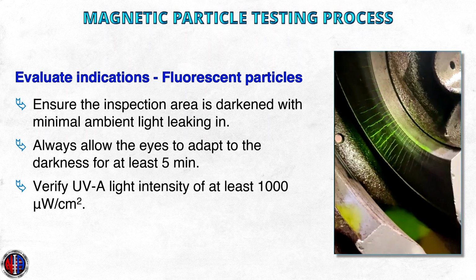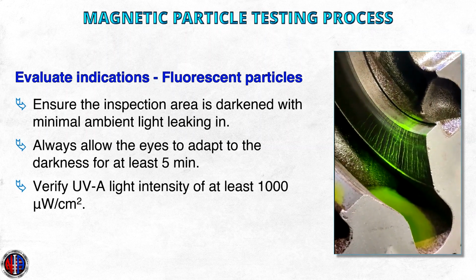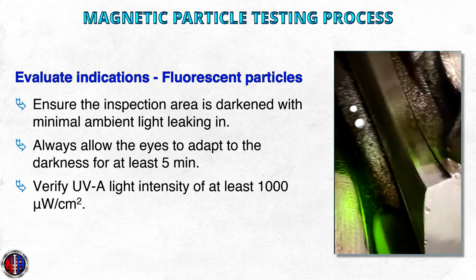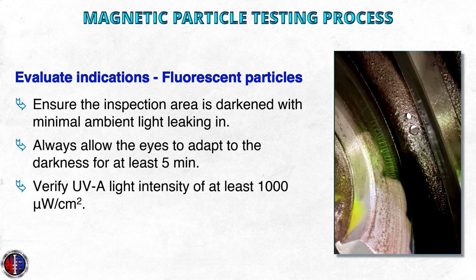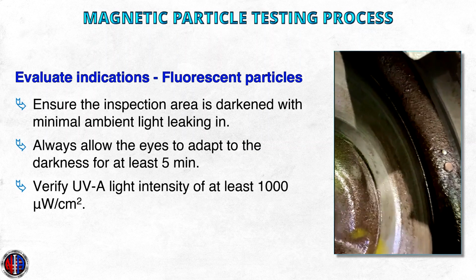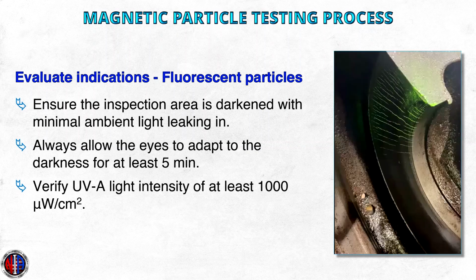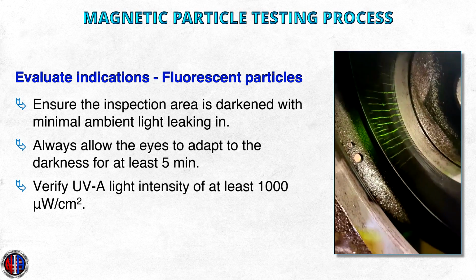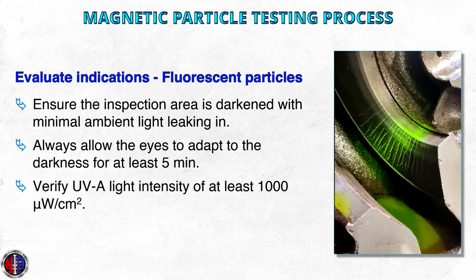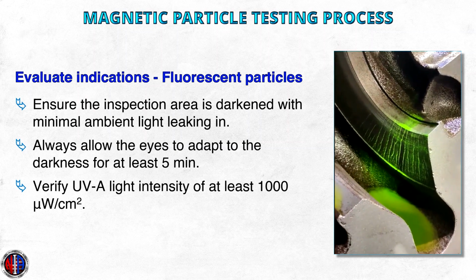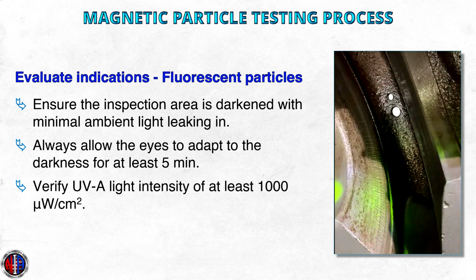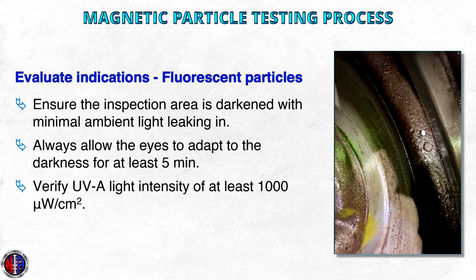As we can see from this video here, we can observe the magnetic particle indications as we shine the black light on the area, but because we are in a rather bright area and it is not properly subdued, as soon as the UVA light leaves the area of the MT indications, they disappear. This is why we want to do this fluorescent magnetic particle testing in a very subdued light condition.